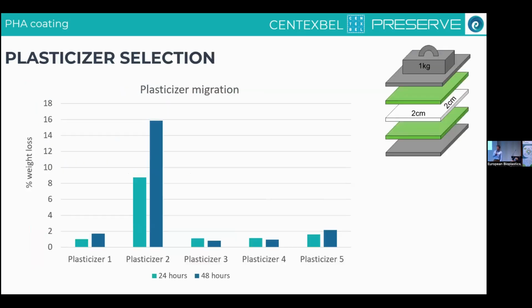Now then, since we are working with food, and I mentioned plasticizer, some of you might be thinking, but what about plasticizer migration? It's quite an important aspect, and it's something we did a lot of screenings about. But this is a summary of the results. What we tested is how the plasticizer migrates onto an absorbent material at elevated temperature and under the pressure of some weight. And you see that for some plasticizers, for example plasticizer 2, after a day or after 2 days, 16% of our plasticizer has migrated out, which is a whole lot and definitely not acceptable. However, if we switch to different plasticizers and different plasticizer blends, this goes to well below 1%.